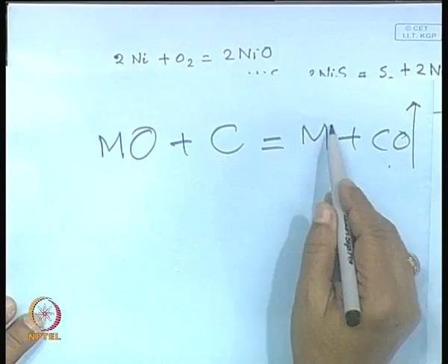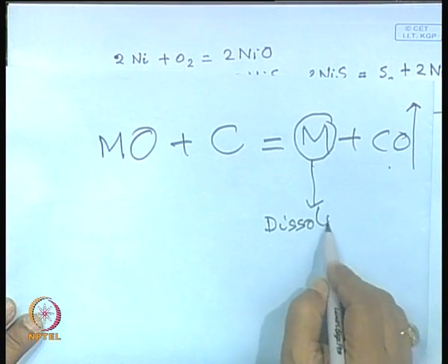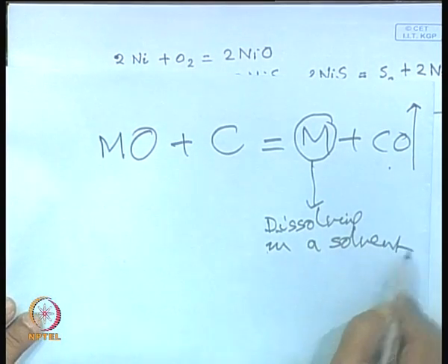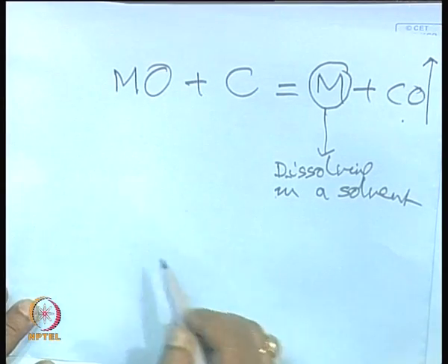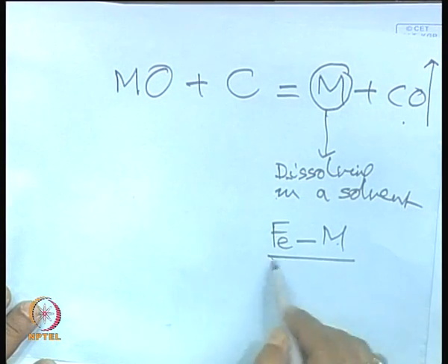The other way would be, if you can lower the activity of M by dissolving it in something. For example, suppose we produce not the metal, but a ferroalloy, a metal dissolved in a pool of iron, then the activity of metal will go down and the reaction will be driven to the right. We will be able to carry out the reaction at a lower temperature. We will also eliminate, if not totally, partially, the tendency to form a carbide, because again formation of a carbide will depend on